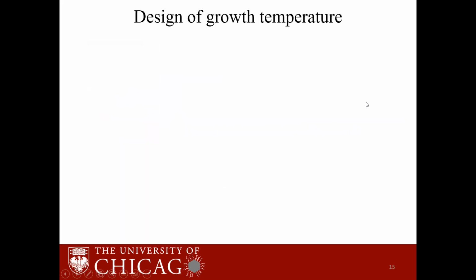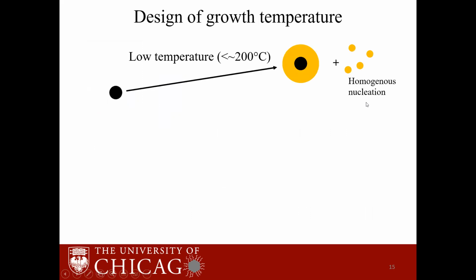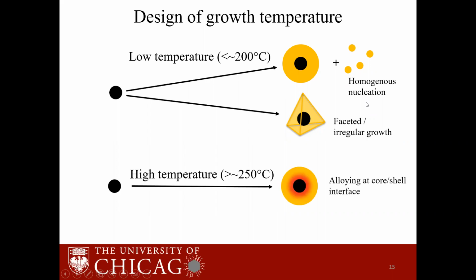semiconductors like mercury selenide. And through our work, we found that the most important criteria for growing a thick shell is the growth temperature. If the growth temperature is too low, then we observe independent nucleation of the shell precursor in the solution, and they will not grow on the core materials. And if the growth temperature is too low, we also see a faceted growth or an irregular shell morphology. But if the temperature is too high, then we see alloying between the core and the shell, and this will lead to changes in the optical properties of the core, all of which we want to avoid.